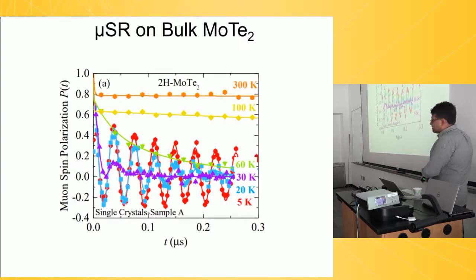Good. So here's molybdenum ditelluride, and here is the data. And here was the big surprise. If you go down here, this is at 5 Kelvin, we saw beautiful oscillations. And beautiful oscillations tells you that the moment in the sample is uniform. So moly ditelluride 2H semiconducting is a magnet. And we can tell from the size of these oscillations that about 40% of the sample is magnetic. It's not 100% magnetic, but that part of the sample that is magnetic has a nice homogeneous field.